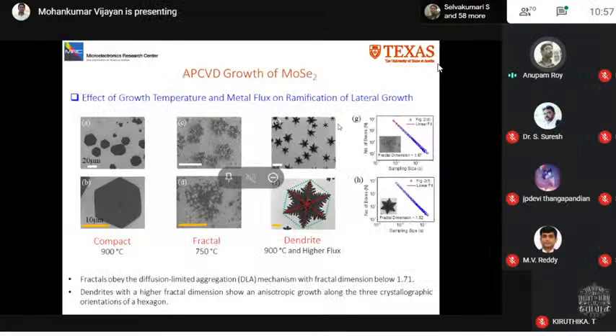Now, at the low temperature, the edge diffusion is highly suppressed, but the incoming atoms continue to attach to the domain edges predominantly via the diffusion limited aggregation process. And since there is no effective reshaping due to reduced edge diffusion, the compact domains generally branch out into fractals. And the fractal dimension calculated from the fractal structure grown at 750 degrees C is about 1.67, as you can see in figure G, which is very close to the 2D DLA fractal dimension, which should come around 1.7. So this shows that the growth at 750 degrees C follows mostly the DLA mechanism.